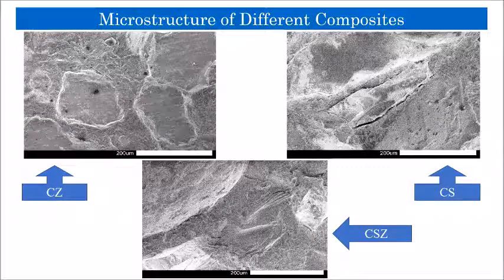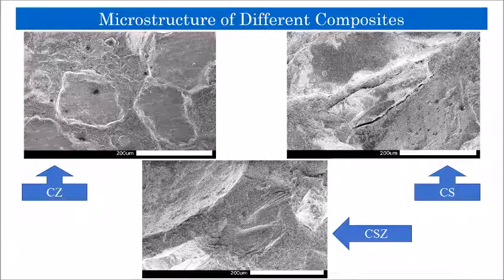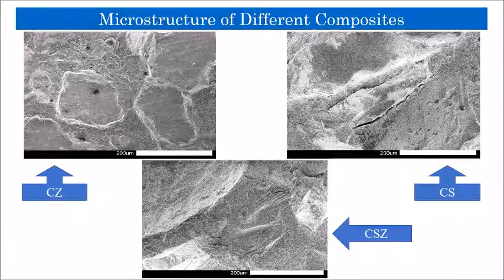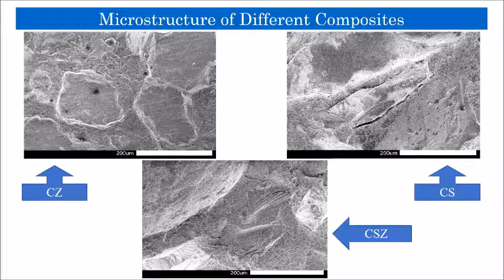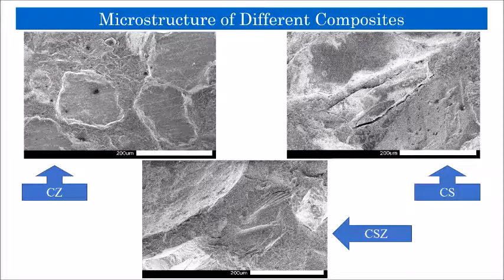These pictures exemplify the microstructure of the three composites prior to thermal shock. We also performed pre-shock post-shock microscopy on these composites and concluded that some of the existing cracks may enlarge, some may shrink, and some may initiate due to thermal shock.